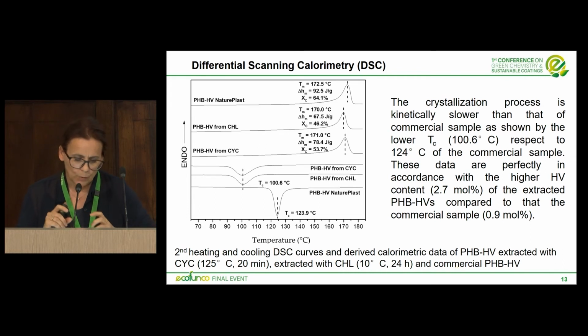You can see that we have a lower crystallinity in the case of the PHB extracted by chloroform and cyclohexanone with respect to the commercial PHB-HV, and this is in accordance with the higher HV content, about 3 mol% of the extracted PHB-HVs compared to the commercial sample, about 1 mol%. And also the crystallization process is kinetically slower than that of the commercial sample, shown by the lower crystallization temperature with respect to the crystallization temperature of the commercial sample.